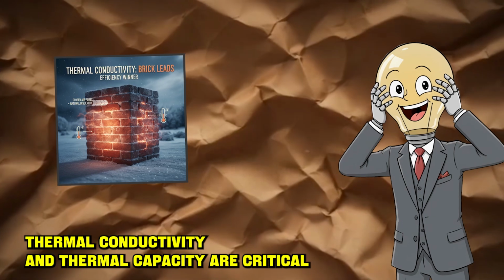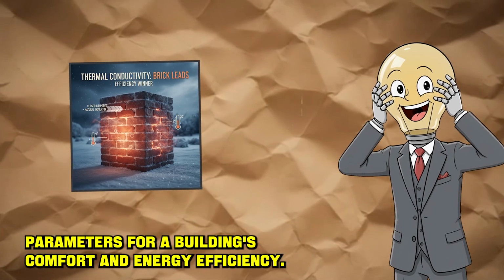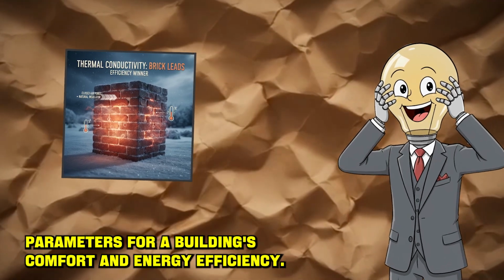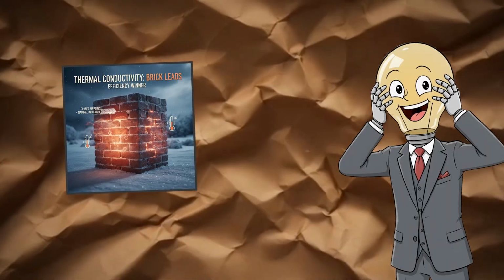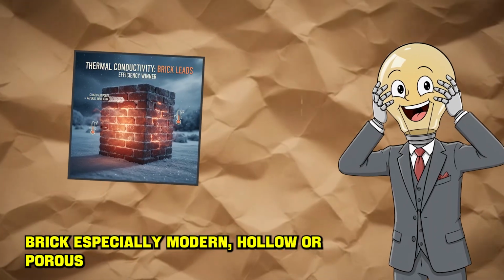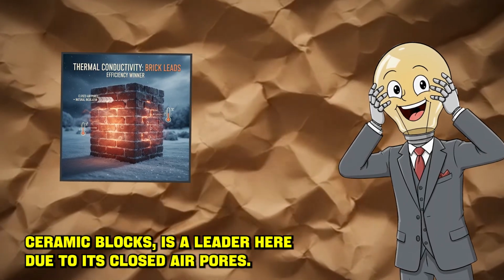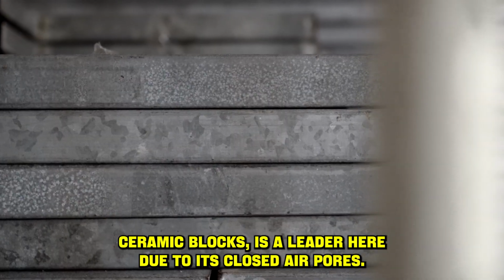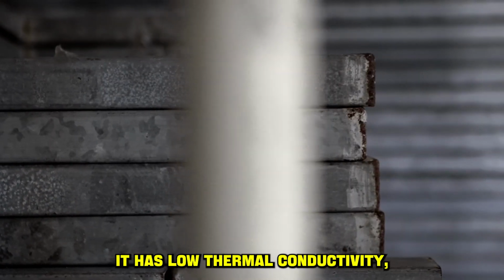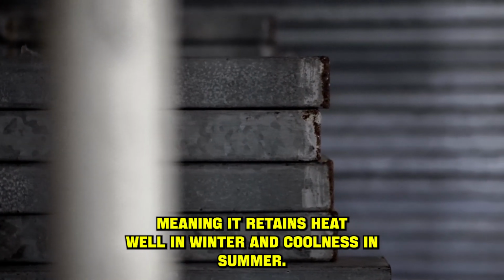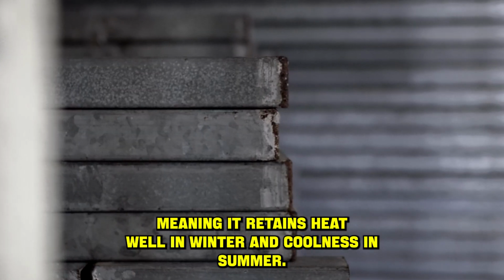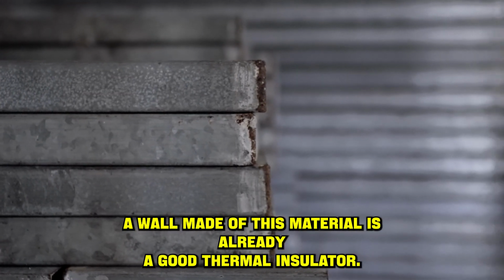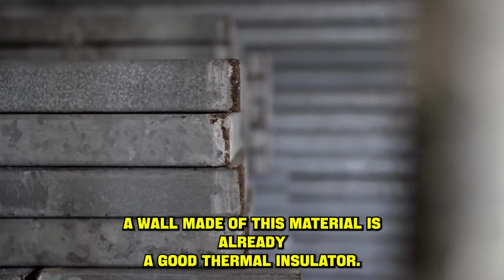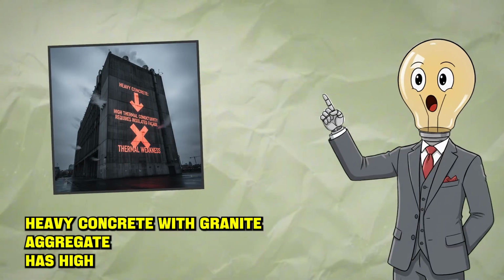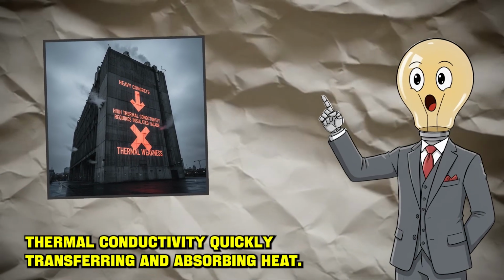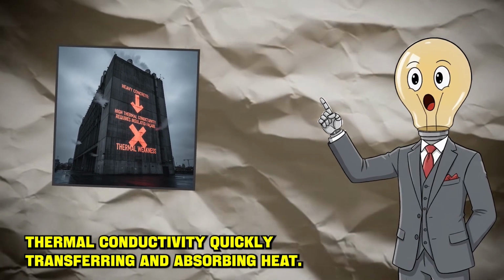Thermal conductivity and thermal capacity are critical parameters for a building's comfort and energy efficiency. Brick, especially modern hollow or porous ceramic blocks, is a leader here. Due to its closed air pores, it has low thermal conductivity, meaning it retains heat well in winter and coolness in summer. A wall made of this material is already a good thermal insulator. Heavy concrete with granite aggregate has high thermal conductivity, quickly transferring and absorbing heat.